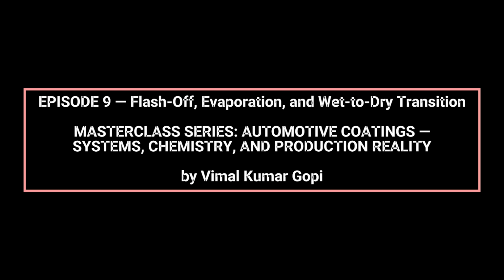In primers, flash-off primarily controls solvent entrapment and film continuity. Insufficient flash-off traps solvent beneath the surface, leading to popping, blistering, adhesion loss, or intercoat delamination after bake. Excessive flash-off, on the other hand, increases viscosity too early, reducing leveling and increasing orange peel transfer into subsequent layers.